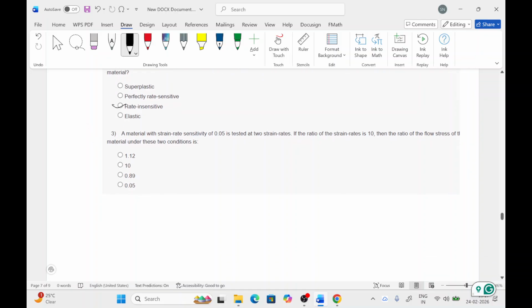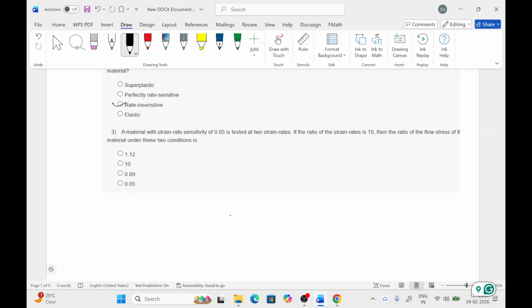Next, a material with a strain rate sensitivity of 0.05 is tested at two strain rates. If the ratio of the strain rates is 10, then what is the ratio of the flow stress of the material under these two conditions? We just have to find sigma 2 by sigma 1, which is epsilon 2 dot by epsilon 1 dot raised to power m. We have given the ratio 10, raised to power 0.05. So this is equal to 1.122. So the first option is correct.